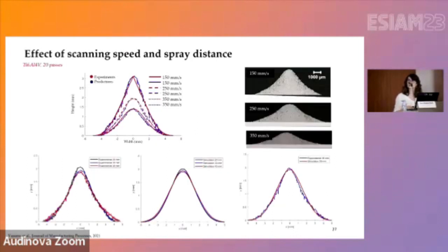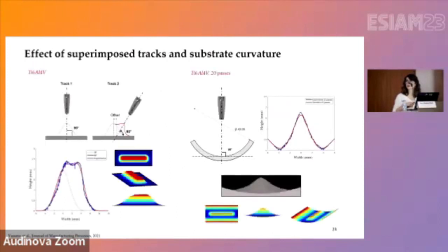The effect of scanning speed and spray distance. Again, all these parameters are affecting the shape, the height, and the width of the deposit. So the model is able to get also this data with a very good fidelity, and also the effect of superposition of different tracks or using a curved shape substrate and how much it would affect the shape of the deposit as we are increasing the number of passes.